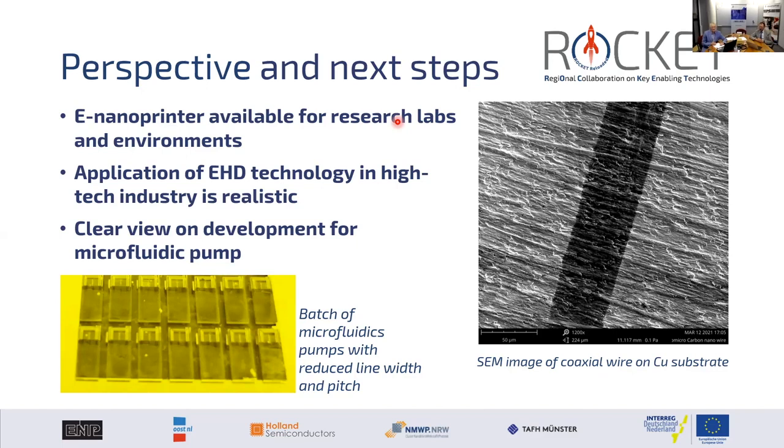Now, the benefit of electrospinning actually is that it's atmospheric, so you don't need high-cost vacuum tools. It's direct write. It's fast. Pulling the jet can go up to a high speed, like 5 meters per minute or so, or it can go pretty fast. So it is an inexpensive, straightforward additive technology, which could yield a direct write solution, which is promising for this application.